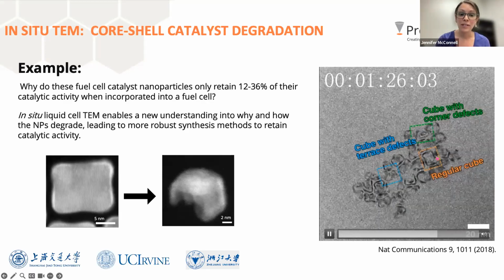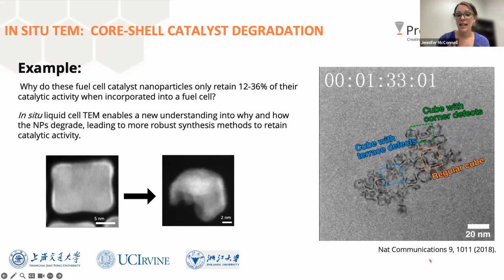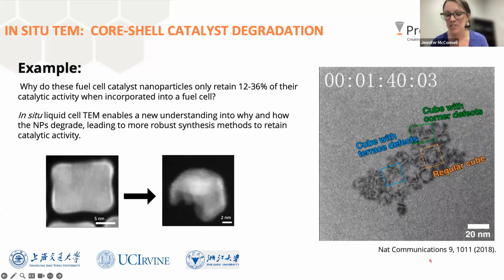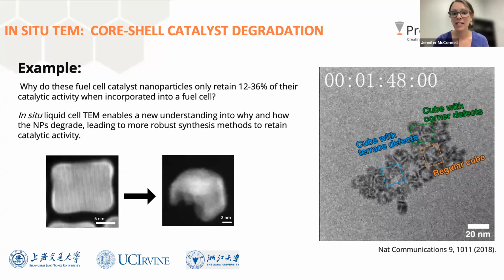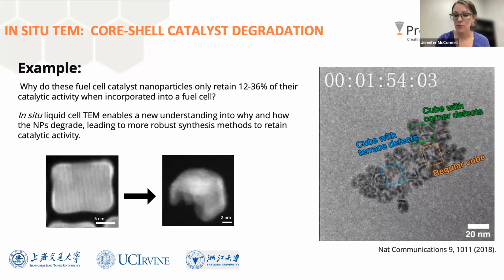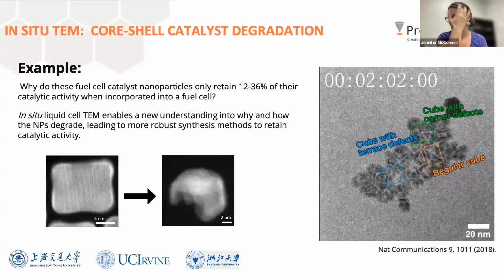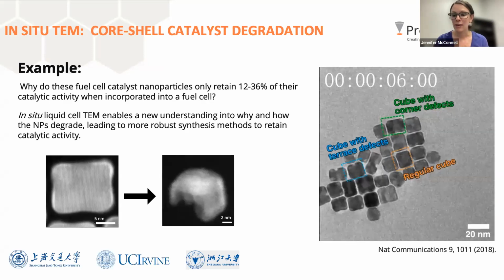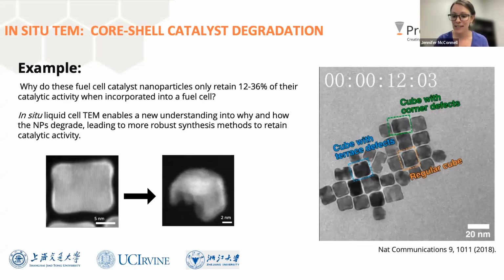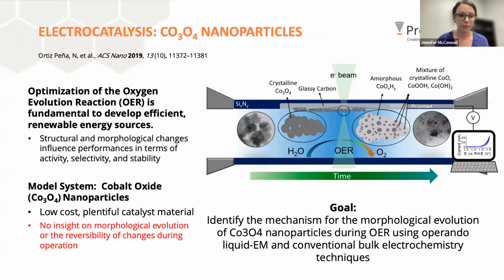Whereas the one without the defect here maintains, for the most part, its shape and probably some catalytic activity for a much longer time frame than those with the defects. And so they were able to see this and understand which defects cause the degradation, and hopefully we can synthesize without them in the future.